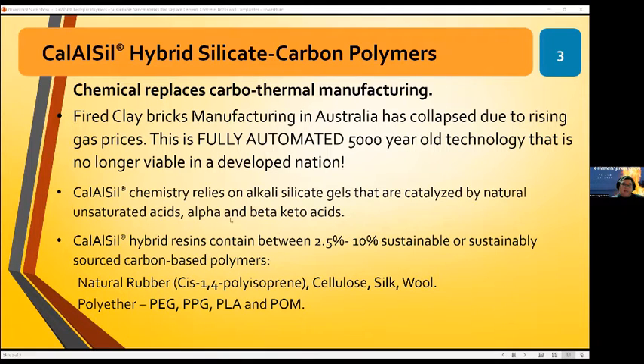Essentially, the chemistry that underpins the hydrogel, or the alkali silicate gels, as I've written it here, are essentially unsaturated acids. So I use them as a catalyst to order the silicate materials or silicate oligomers in the water solution. Now, this obviously is very difficult to identify, and I'll go through some things that we have identified, but nanostructures in water are very, very difficult to identify using any of the chemical or spectrometric techniques that we have. Essentially, when you start adding many different components to a system, it makes it almost impossible. So I'll get to that just in a moment.